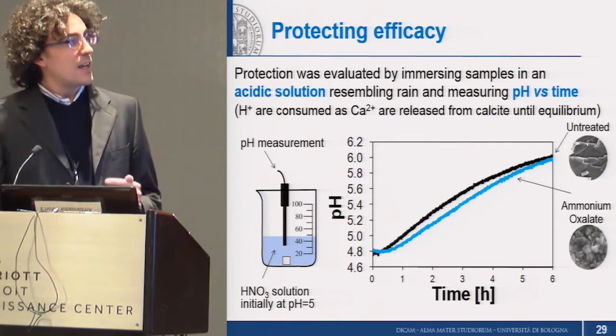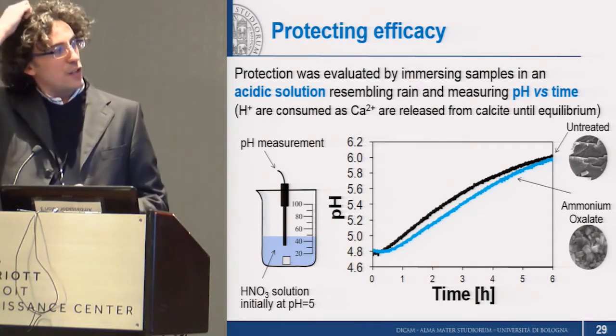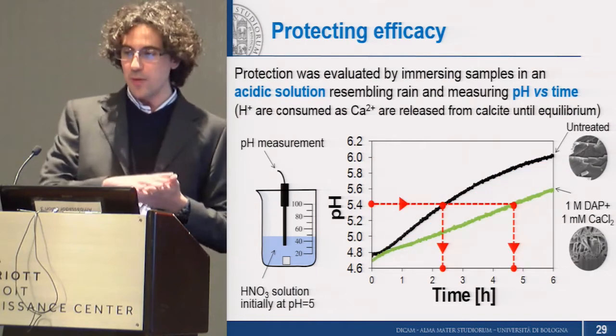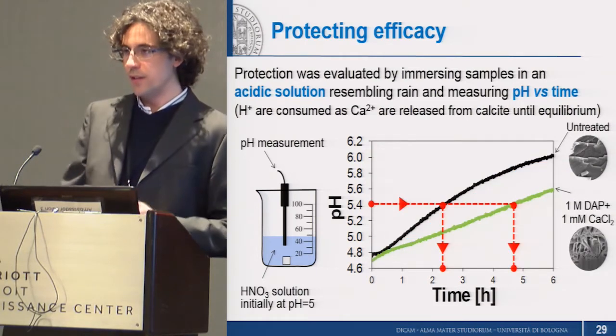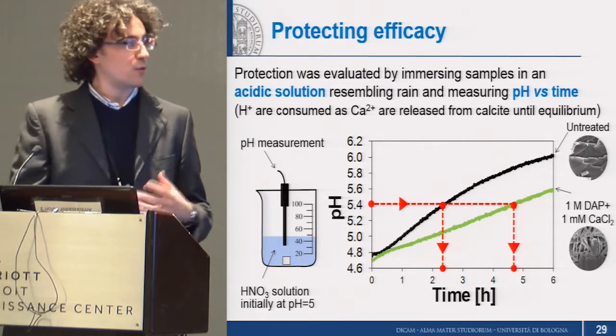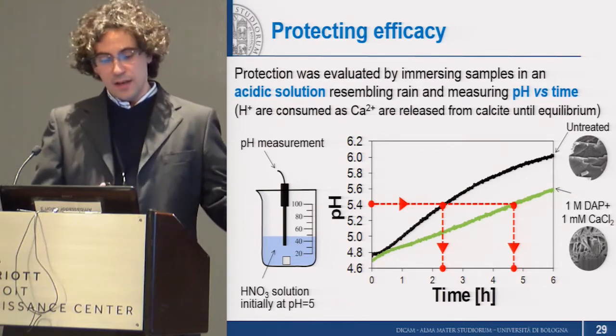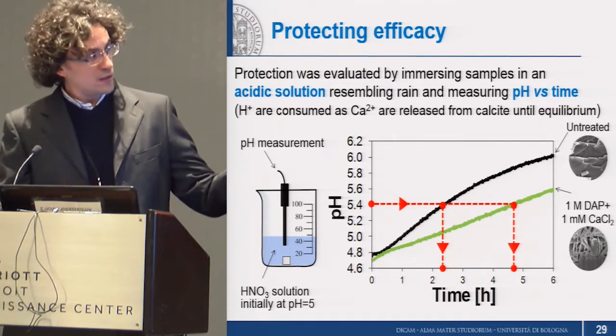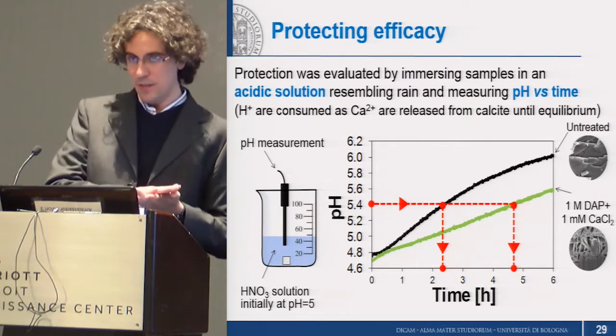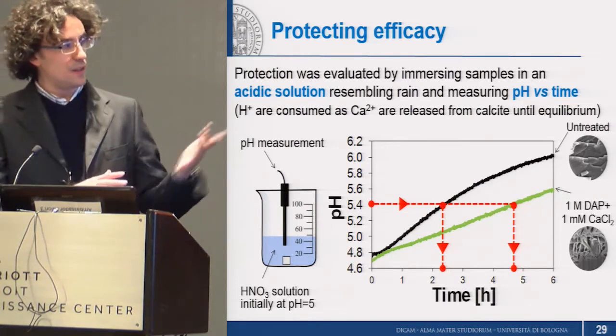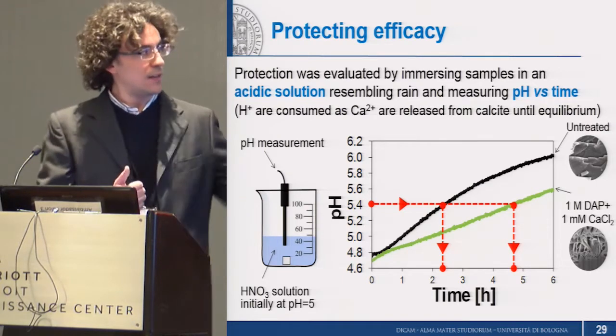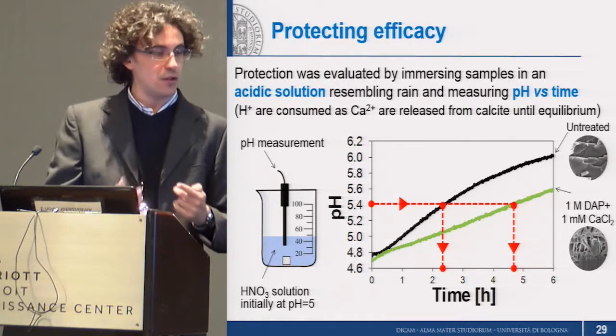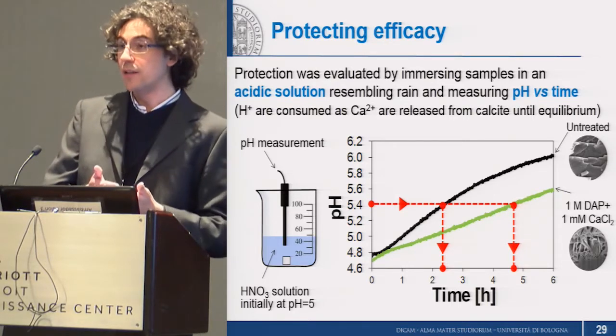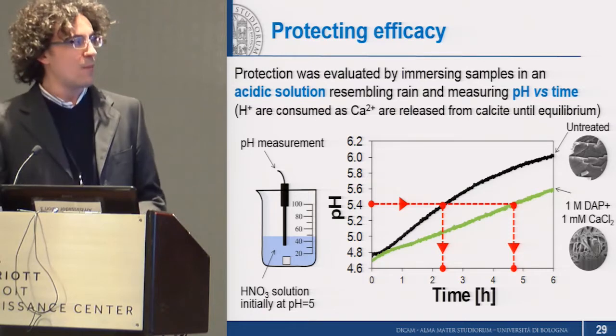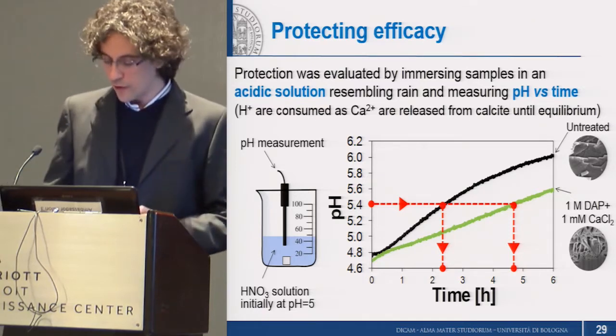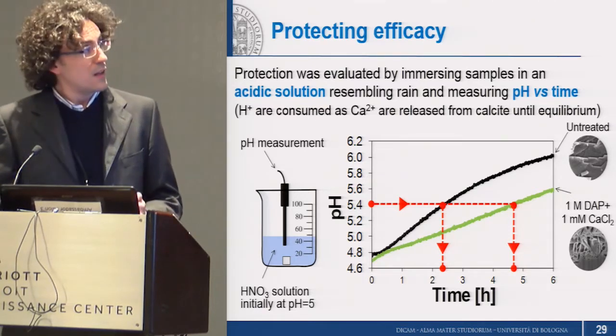And this was the case because, let's say that starting from the treatment with simply DAP and calcium chloride, with no ethanol addition, we get a quite coarse, quite porous microstructure. So we were able, unfortunately, not to completely inhibit marble dissolution, but still to delay it quite a lot. Let's say that for reaching the same pH level, it took basically twice as long. So we were able to provide our marble, our monument, with a good increase in durability.